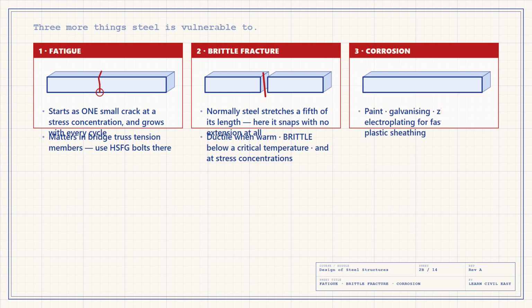Brittle fracture. Steel is ductile. It can stretch by about 1/5 of its original length before it fails. But sometimes it fails suddenly with almost no extension at all. 2 causes: steel is ductile when warm but brittle below a critical temperature, and a zone of stress concentration will develop a brittle fracture. Ductile failure warns you, brittle failure does not. That is precisely why IS 2062 gives you subgrades.